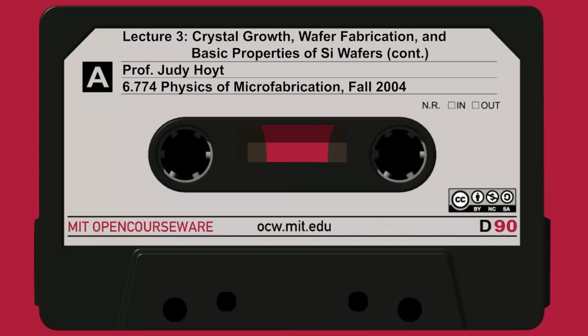And in fact, we'll see that in the chapter on diffusion. We'll see what are called Fermi level effects. People move the Fermi level up and down, and when it's up really high, all of a sudden the diffusivity of arsenic goes way up. And the explanation is related to the fact that you've just stuffed the crystal with a lot more vacancies.